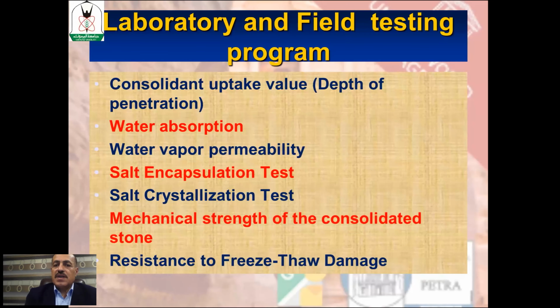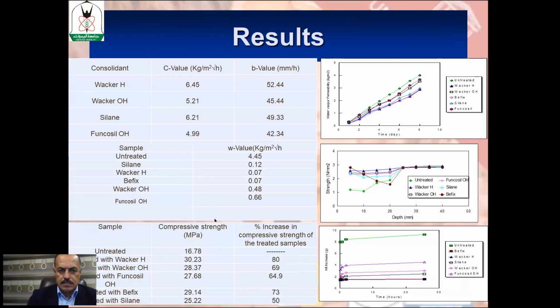So our laboratory and field testing program includes a series of tests like consolidant uptake value, depth of penetration, water absorption, water vapor permeability, salt encapsulation test, salt crystallization test, mechanical strength, and resistance to freeze-thaw damage. And the results really show that most of these consolidants lead to an improvement, especially in the compressive strength of the stone. For example, there is a big